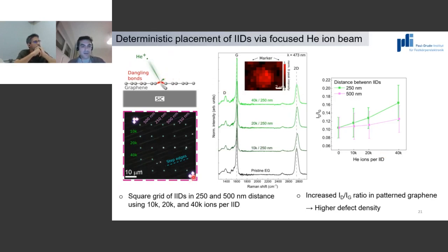So let me just show you what we did. We have a pattern created by optical lithography with some markers, which leads to this square here. And in the middle, we create an ensemble of defects with different distances and so on. For these defects, we use different amounts of ions per irradiation-induced defect, what I call here IID. We use either 10,000, 20,000, or 40,000 ions per IID. And this is what is in this pattern. So the pattern is not important.